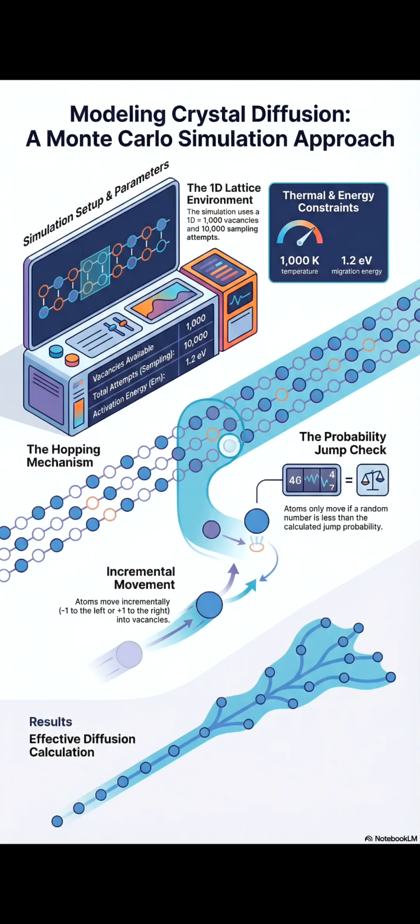In the context of solid-state diffusion, that is absolutely screaming fast. Oh, yeah. For comparison, if you looked at self-diffusion in real copper at a comparable temperature, you might see a coefficient in the range of 10 to the negative 13th or 10 to the negative 14th. Wow, so our simulation is orders of magnitude faster. Is that just because of the 1,000-degree heat? The heat is a big factor, yes.